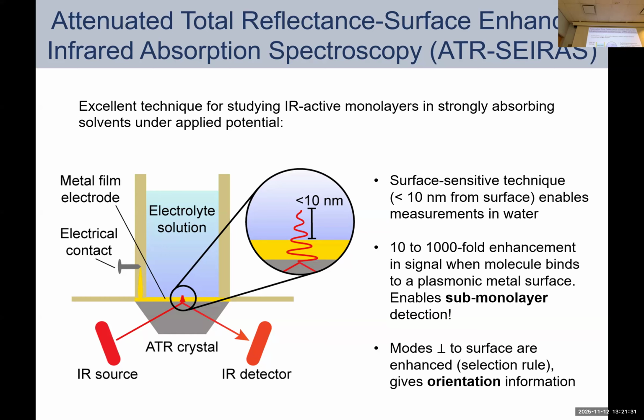Okay, but this is great now because we can perform experiments in solvents that are very strongly absorbing, and we can essentially cut out a lot of that noise from all of the solvent above if we're looking at larger enhancements from molecules that are specifically absorbed. Now, the enhancement is about 10 to 1,000-fold enhancement in signal compared to a molecule that is not absorbed to, or that is not being measured using ATR-SEIRAS.